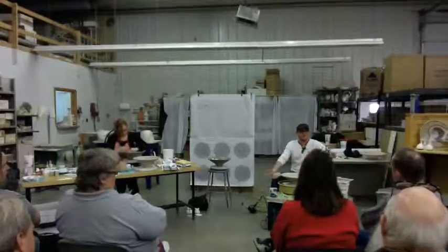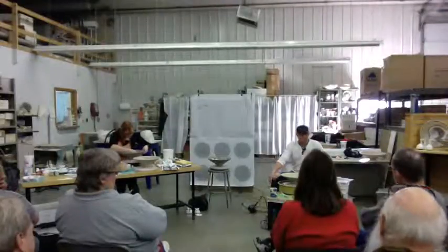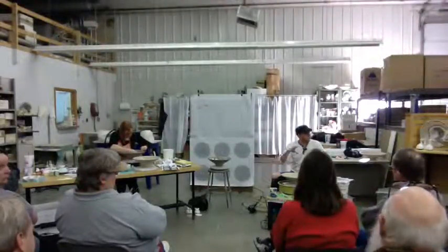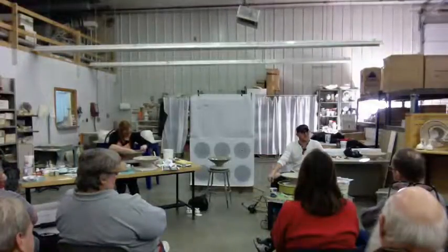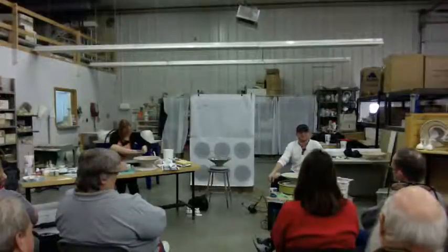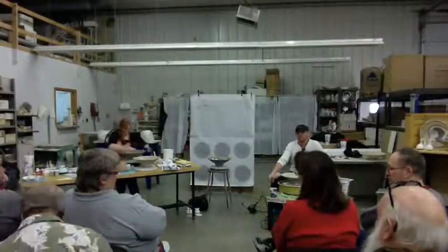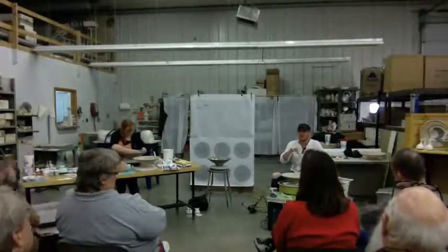I only need the carbon. So I don't need any flashing, I don't need anything like that. And then where the carbon gets really gold on the white crackle, I just use a torch and burn it off. And it makes your pieces a lot whiter than if you scrubbed them under a sink. So you do that while the pot's still hot? I do it while the pot's still hot because I don't want to reheat an area and crack it.